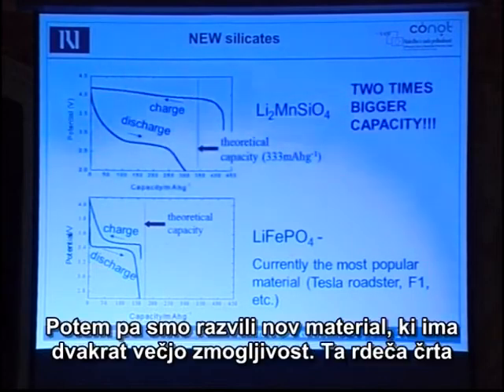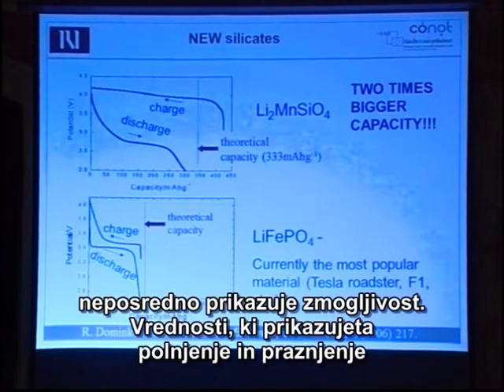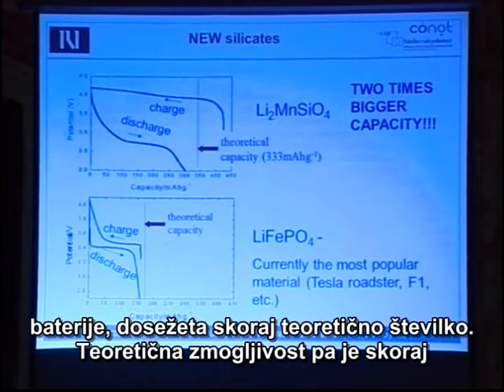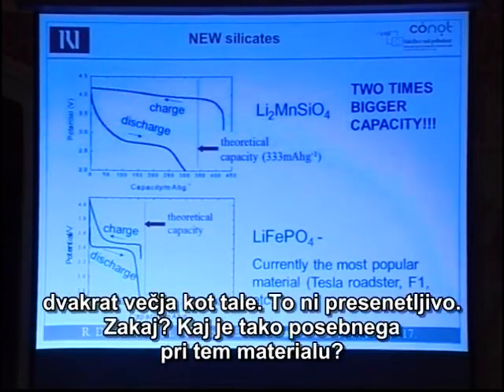Now, what we did is we invented a new material which has 2 times bigger theoretical capacity. So this red line shows theoretical capacity. And you have to look at the lower part. This is discharge. Discharge goes almost to the theoretical number here. And you can see the theoretical capacity is almost 2 times bigger than this one.